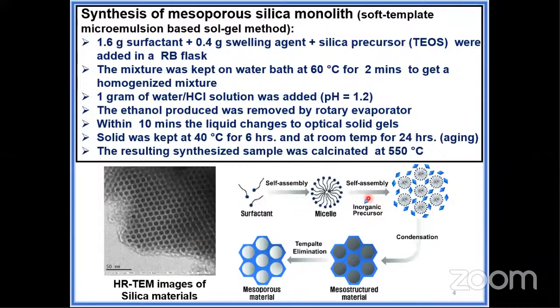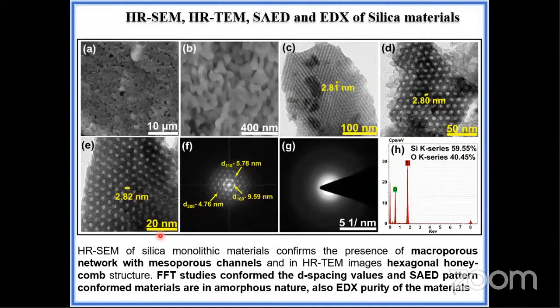When we add an inorganic silica precursor under aging, hydrothermal and concentration processes, we obtain a mesostructured material. After template elimination, we obtain a hexagonally arranged material. In HRSEM, the silica monolithic material confirms the presence of a macroporous network with mesoporous channels. And in HRTEM, it confirms the presence of a hexagonal honeycomb structure network in the material.